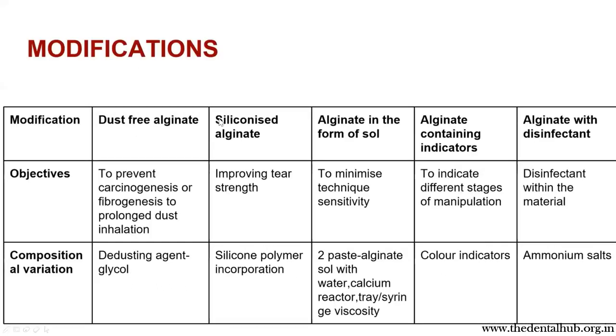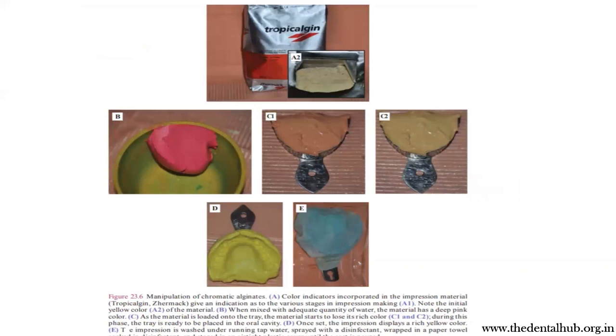Some modifications of alginate include: dust-free alginate, which prevents silicosis from prolonged dust inhalation by addition of a de-dusting agent — glycol. Siliconized alginate improves tear strength by incorporating a silicone polymer. Alginate in sol form minimizes technique sensitivity via a two-paste system. Alginate containing color indicators helps indicate different stages of manipulation. Alginate with a disinfectant incorporates ammonium salts within the material. One commercial example is Tropicalgin, which shows different colors at different stages — dispensing, placing, loading, and removal.